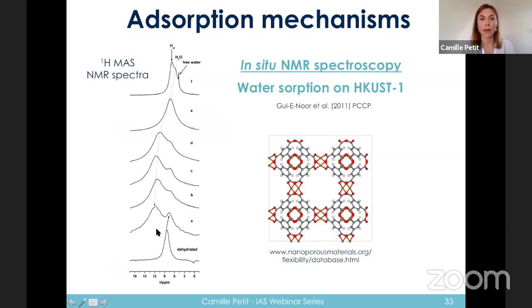I wanted to also highlight the power in a way of in situ NMR spectroscopy. Here in the case of water adsorption on a very common MOF, which is HKUST-1. HKUST-1 has, as MOF 74, which I mentioned earlier, unsaturated metal sites here, so they can interact with a lot of adsorbates, and in particular water. And if you look at the NMR spectra of the dehydrated sample, it's very different from the one that is hydrated. And you can see that depending on the form of water molecules in that material, you'll have different shifts for that NMR peak. And you can therefore distinguish between the different types of water in that MOF.